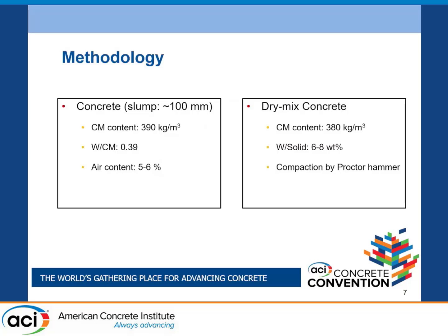For our dry mix concrete, we used cementitious materials of 380 kilograms per cubic meter. We prepared each sample with different water to solid ratios to minimize the amount of entrapped air, because in a dry mix we have a limited amount of paste. Again, because it is a dry mix, the samples need compaction, so we used a Proctor hammer to compact our samples.